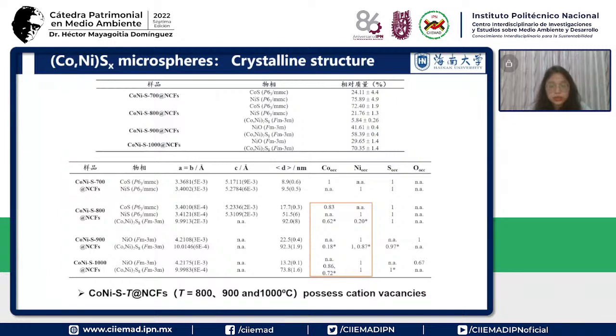Here there are 2 tables to summarize the parameters of the XRD analysis. And here we also get new information. When the temperature is 800, 900, and 1000, these 3 samples have cation vacancies, like cobalt or nickel vacancies.